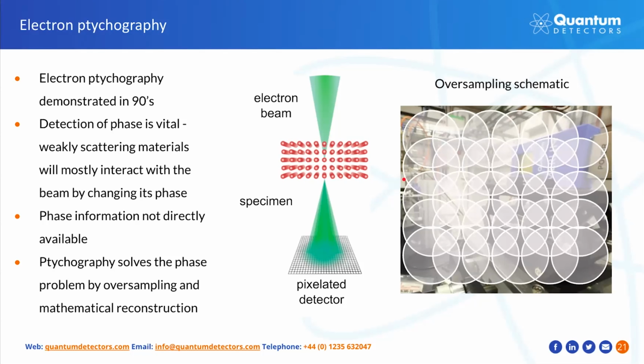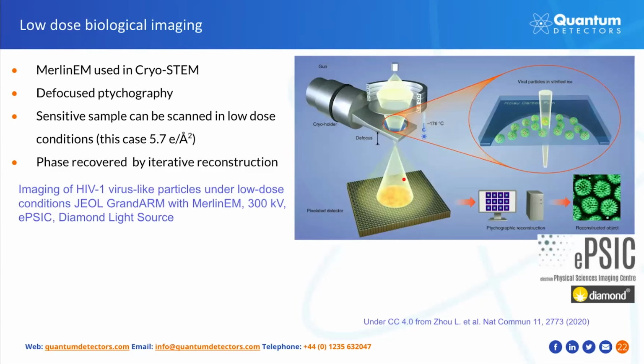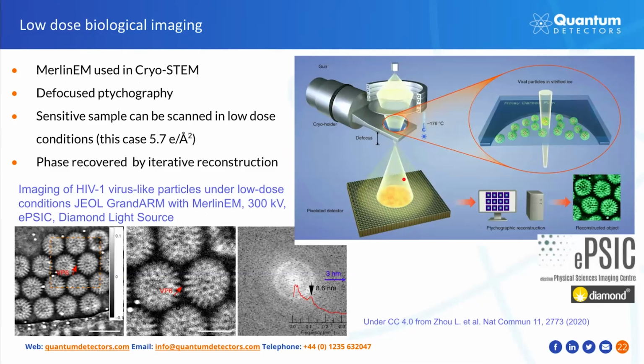As I mentioned before, biological specimens are weakly scattering, so they are a good application for ptychography, and I'll be showing this on this slide. Researchers at ePSIC, Diamond Light Source, have used ptychography with a defocused probe to image HIV-like virus particles. This is a significant result because biological imaging is usually done in transmission electron microscopy, so not scanning the beam over the sample. By defocusing the probe, a low dose of 5.7 electrons per angstrom squared was achieved, and the sample was not damaged in the process. In this case, the MerlinEM detector was used to image with a 300 kV probe in a material science focused microscope with a cryogenic holder.